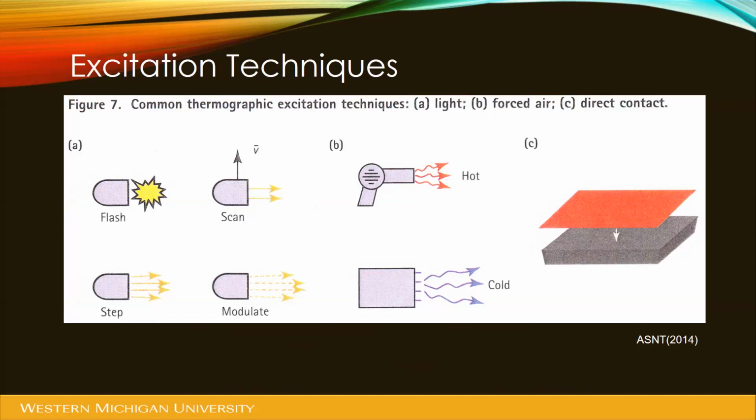Scanning there is a light, and we want to look at an object that's heating up or cooling down. So if we take a light that's on or a heat source that's on and we move it across an object, if my point that I want to scan is where my water bottle is here, if I move this light across, right, it's going to start to heat it up, and then it's going to cool off, right? So it creates a heating and a cooling as I scan past. So I point my camera at it, and I run that light back and forth. You can actually watch it change temperature, even if it's a very small temperature rise.